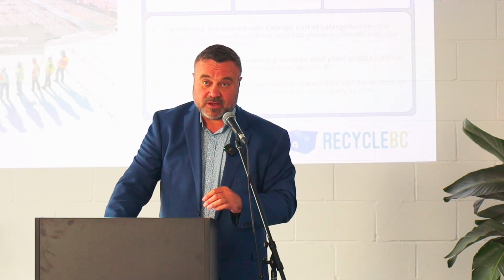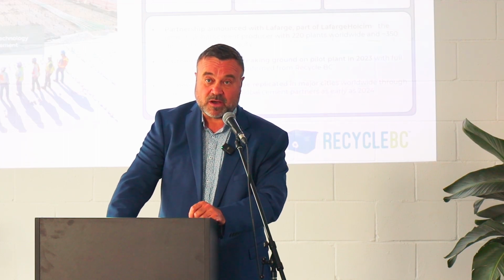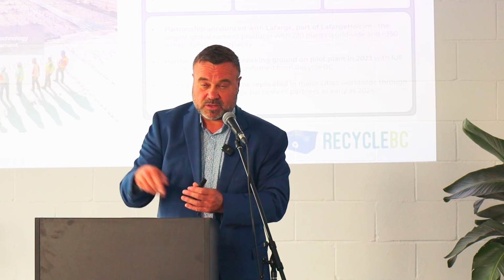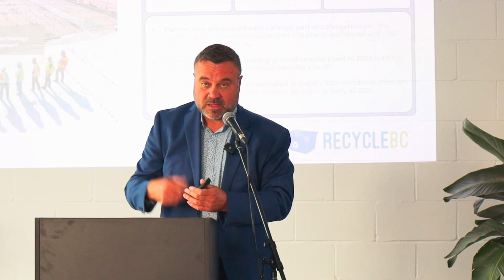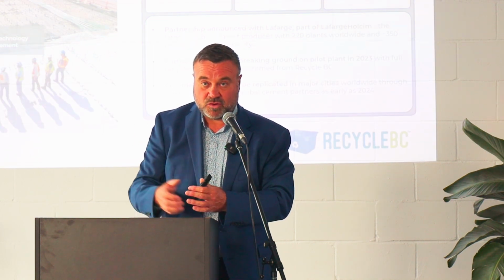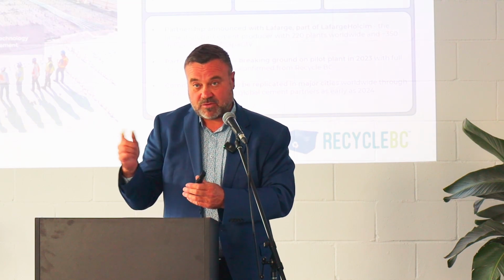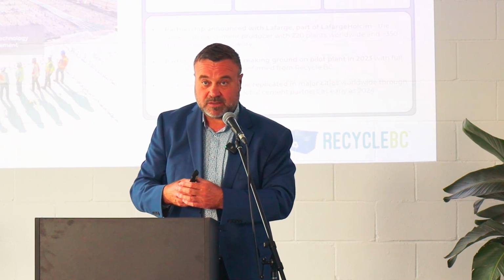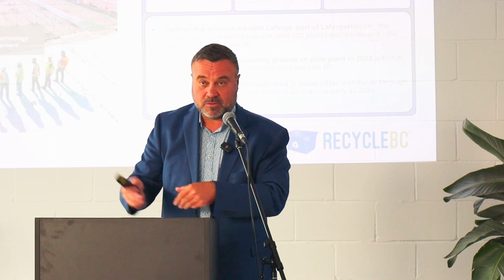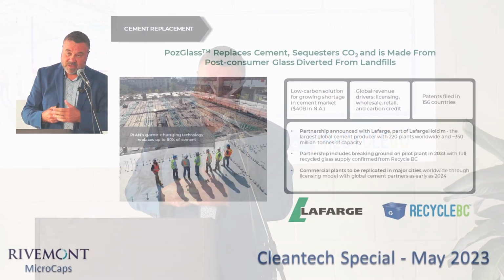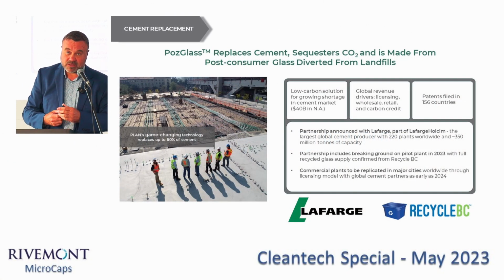So our team figured out that if we grind the glass very small, and we do it in a wet environment, we will release the sodium from the surface of the glass particle. And then that wastewater, if we bubble CO2 through it, we make sodium rocks again. We reverse the process of making cement, and we turn CO2 into a rock. We have patents pending in 156 countries. Ground glass as a replacement for cement has been approved since November 2020.